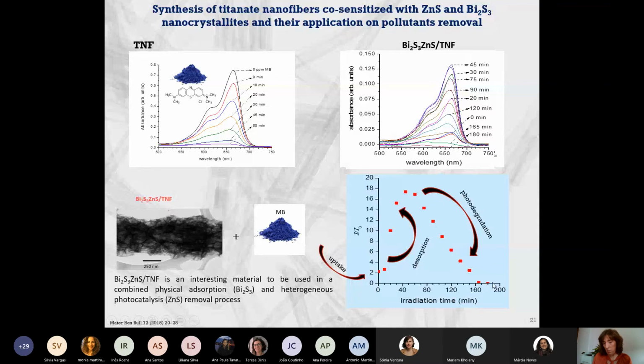And here in the limit, we have completely recovered our material that can be used again to remove dye from a solution. And this is very interesting because we are combining two different processes. Adsorption, we are removing the dye from a solution by adsorption, and then we recover the material by photocatalytic degradation of this dye.